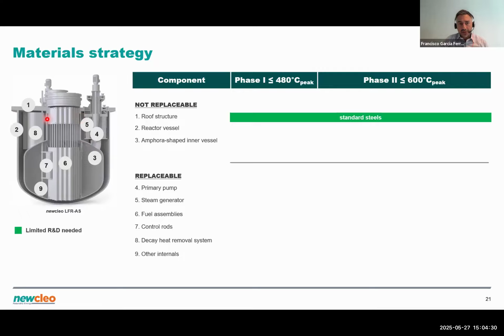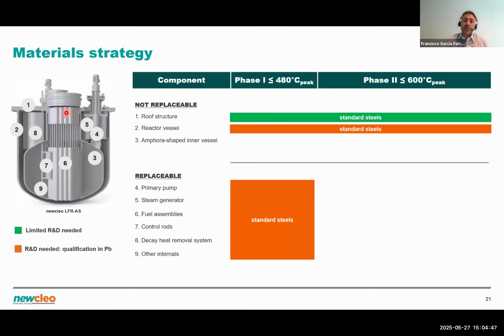So if we look at our reactor and we consider the roof structures, they are not in contact with the lead. So there's essentially very limited R&D needed concerning this type of components, even though there could be some because it's a new system anyhow. But as far as lead is concerned, we don't need to do much. Now, if you look at the reactor vessel and other components which are replaceable, we can still rely on standard steels, 316L for example, but we do need to do R&D. And the reason why is, despite these steels are very well known, we need to show to a regulator that we can utilize these steels in a safe manner and that they are compatible with lead under the specific conditions that we are planning to have in our reactor, with the specific design that we will have. So we do need to do this qualification in lead.